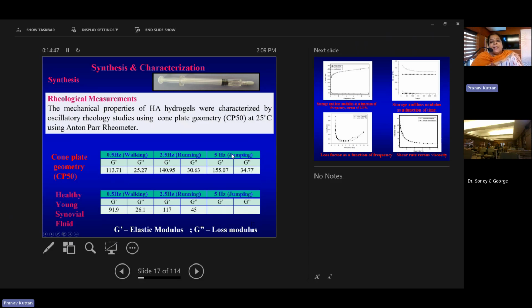And once after developing the gel, we did the rheological measurements. That is, rheological measurements are very important for hydrogels because this is acting as a lubricant, and how this will act when you give a strain or stress to this is very important. So that can be evaluated using the rheological measurements. So that was done using a cone plate geometry at 25 degrees Celsius using an Anton Paar rheometer.